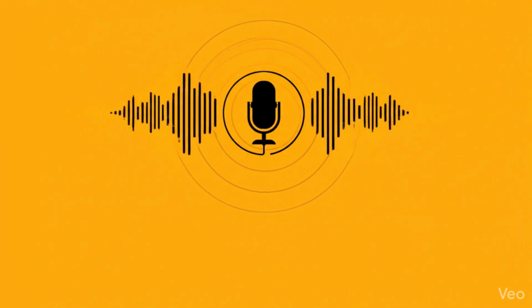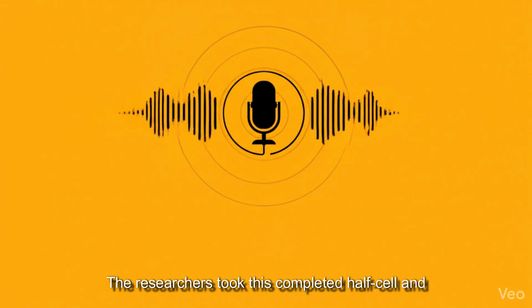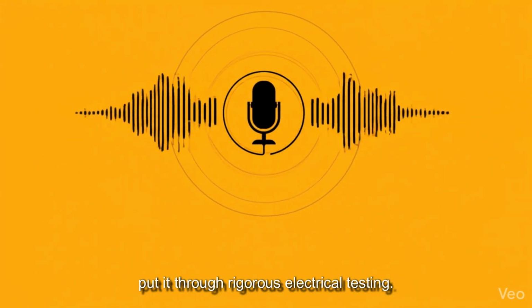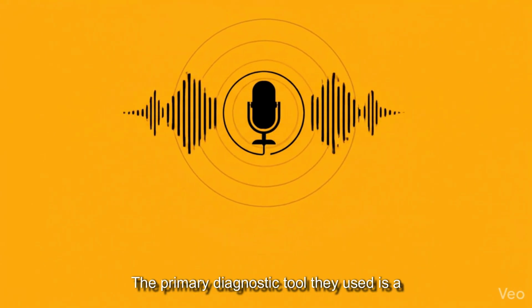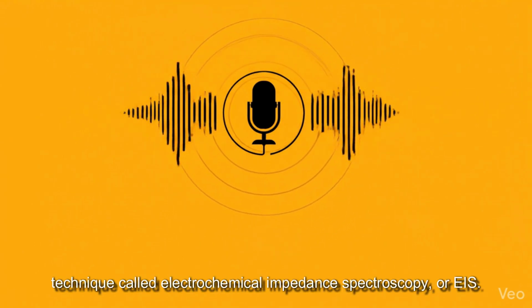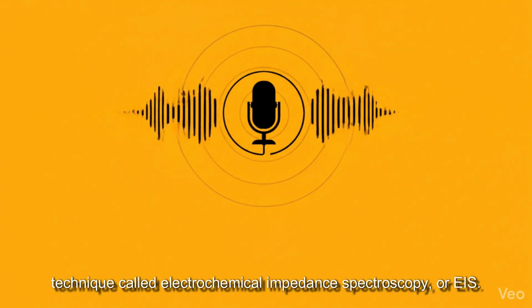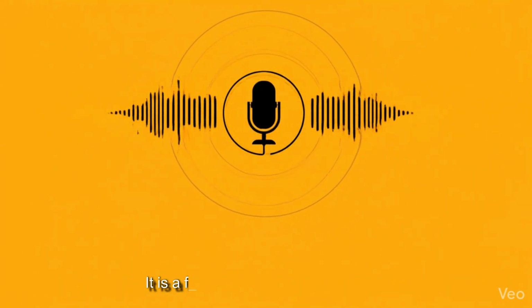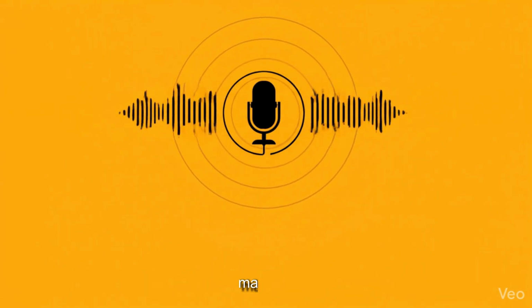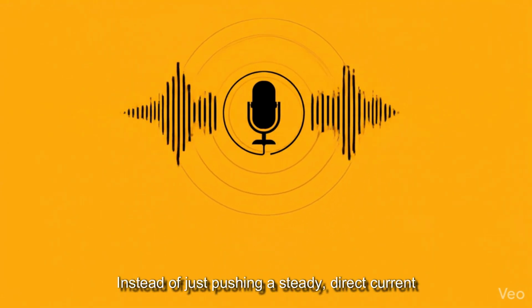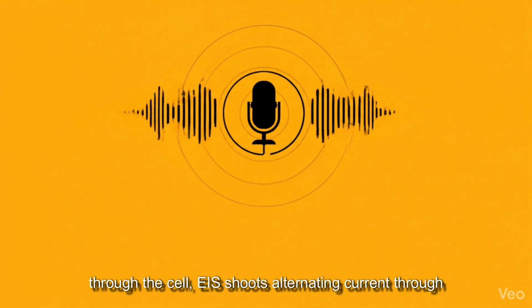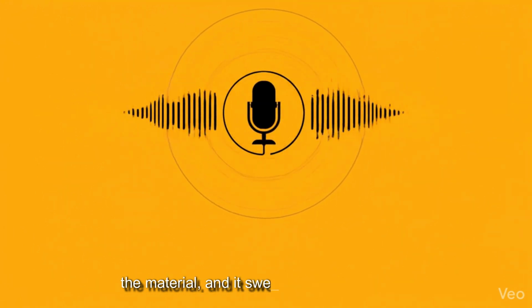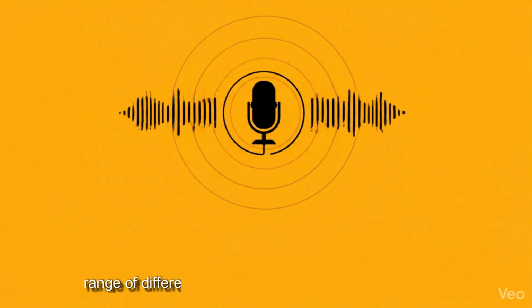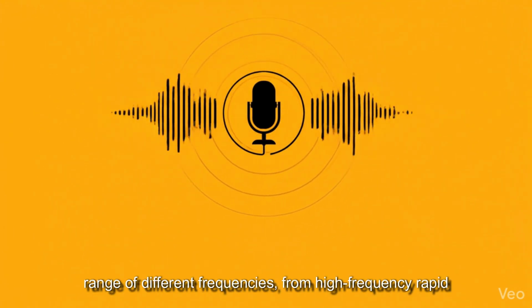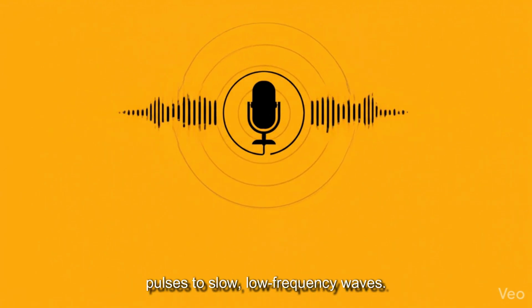Exactly. Did it work? The researchers took this completed half cell and put it through rigorous electrical testing. The primary diagnostic tool they used is a technique called electrochemical impedance spectroscopy, or EIS. It is a fascinating way to interrogate a material. Instead of just pushing a steady direct current through the cell, EIS shoots alternating current through the material, and it sweeps across a massive range of different frequencies, from high-frequency rapid pulses to slow, low-frequency waves.